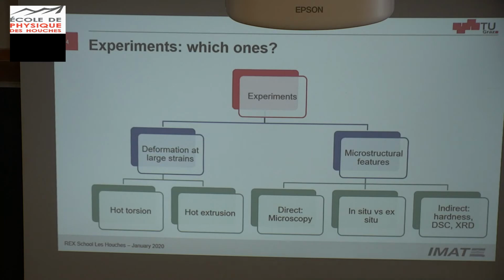And microstructural features, you may have direct, so you classically open the material and take a look at it. So this is microscopy, any type of microscopy, mainly for dynamic recovery. We use a lot of EBSD. Then you have other methods, indirect methods. They are not much used. I know that Andras is working a lot on XRD, but you may also have differential scanning calorimetry to get a account of stored energy, for example, or hardness. It's a very simple method, hardness, but gives a lot of information about stored energy.